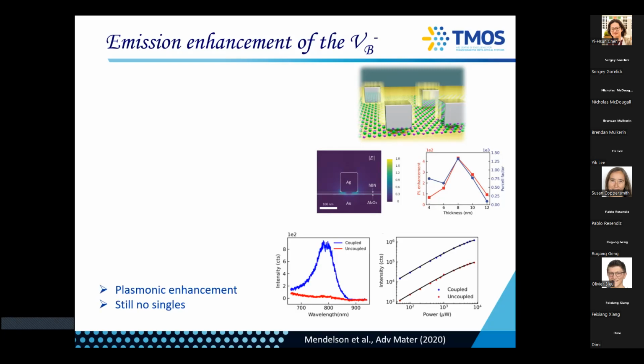And so you can indeed measure enhancements, quite high. Actually the highest I've ever seen, about 20, 30. And you can see this is one example where you have a coupled and an uncoupled emitter that you can barely see. So these are experiments that are done in a way blind. You irradiate your hBN with a very low dose. You don't really see the emitters. Once you put the cubes, everything shines up, but still no singles. So our aim to generate single VB centers is still not solved.